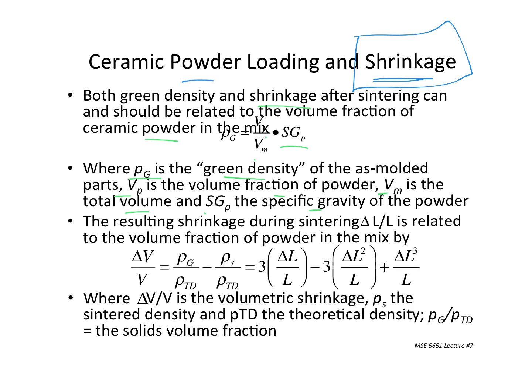What we're really focused on here is the shrinkage during sintering. And what I'm showing you here is a classic relationship between a linear shrinkage, delta L over L, which is important to us because we can measure this. We can put this part in the dilatometer, and we can figure out delta L over L. And then we can, with this particular formula, relate that to delta V over V, which is much more difficult to do on a practical basis. Linear shrinkage is not so bad. Volumetric shrinkage can be a real pain. And so we have this expression for delta L over L, where the delta L part of it is first squared and then cubed. And this is related to, again, this green density, the final solids density, theoretical density in both cases, and so forth and so on.